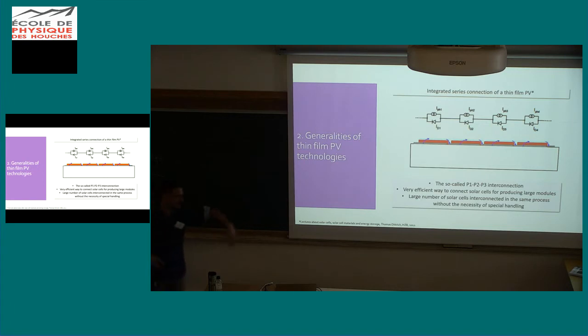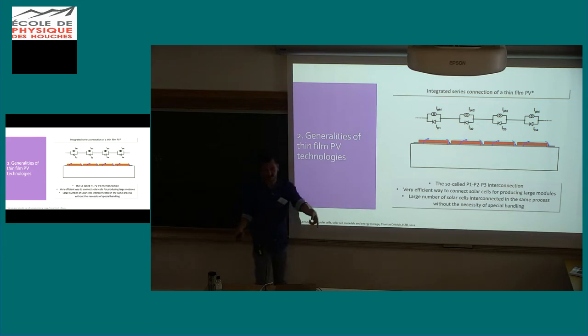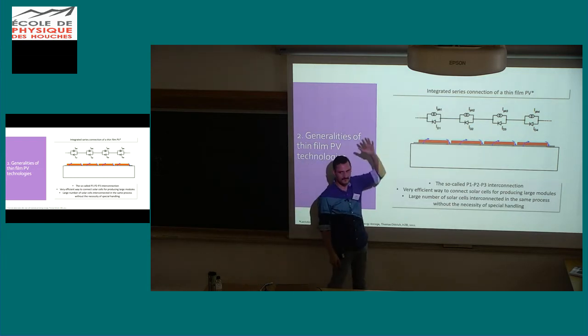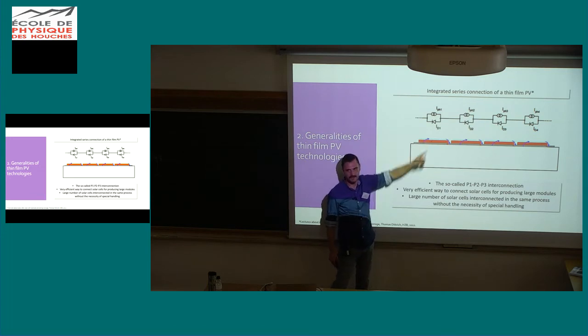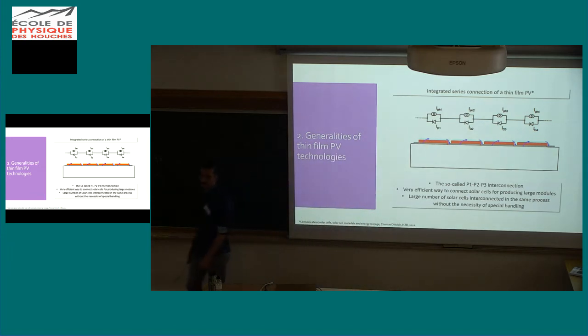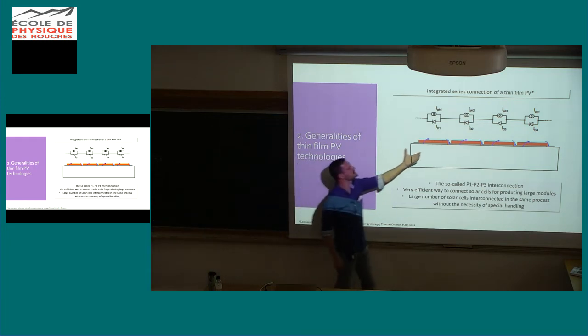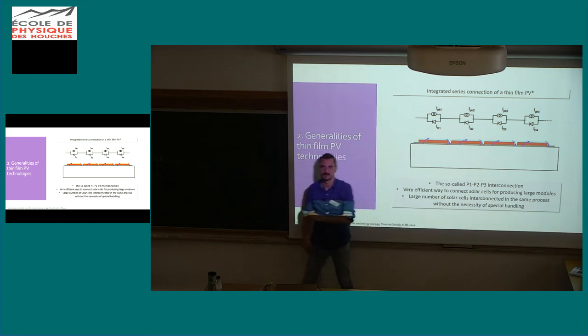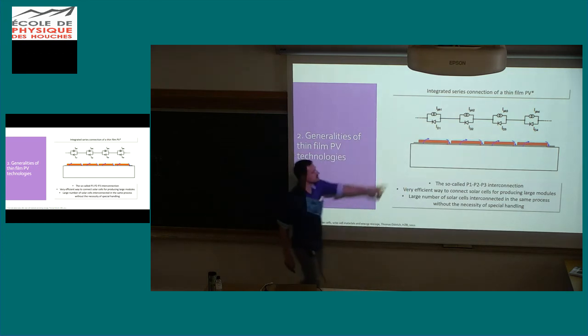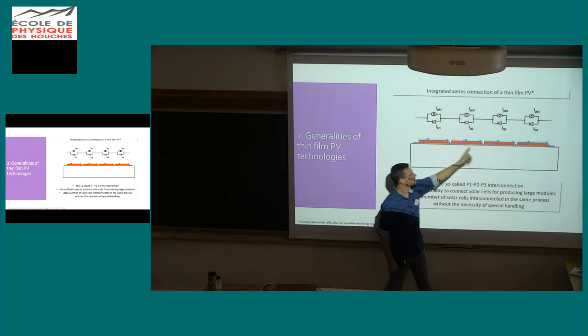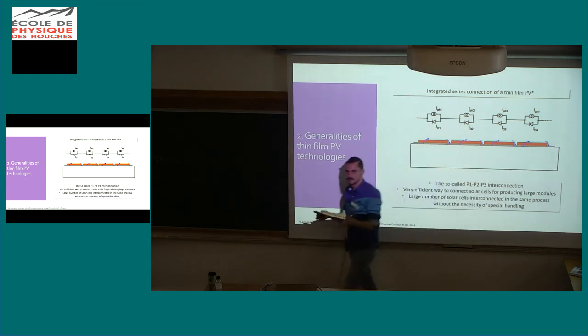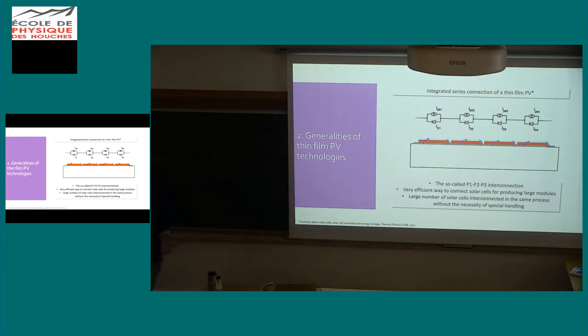So imagine if this is a solar panel, you cannot have a single cell here, because you can imagine how much current 1 square meter can produce, a lot of amperes, tens of amperes, and you have to connect them in a 500 nanometer thick TCO. So it's impossible. So you need to reduce this as much as possible, and 1 centimeter, 2 centimeters is still okay. Then with this strategy, you can connect all these cells, and then you increase the voltage, but you keep the current at a safe value that the TCO can afford.